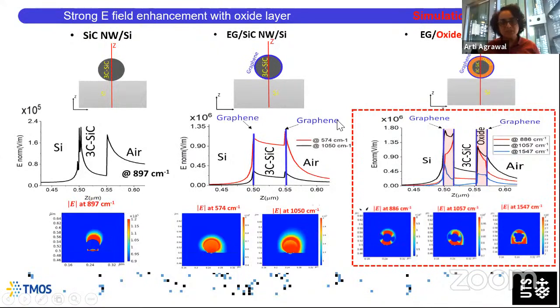What we have achieved by doing this, if you concentrate on the right-handmost column of this figure, here I'm plotting the field inside the oxide layer. You can see that the field drops very sharply outside the oxide layer. This oxide layer is about 4 to 10 nanometers thick, and inside that layer most of the field is concentrated. As soon as you go outside that, the field drops drastically.